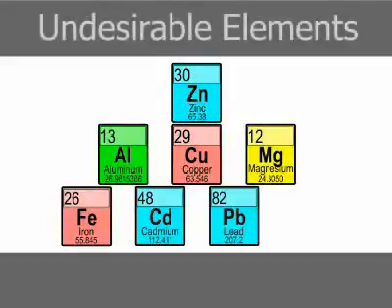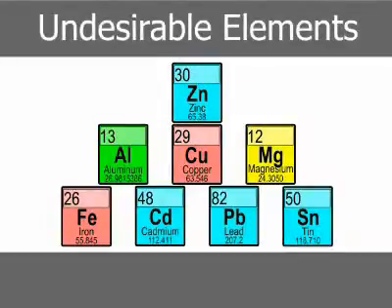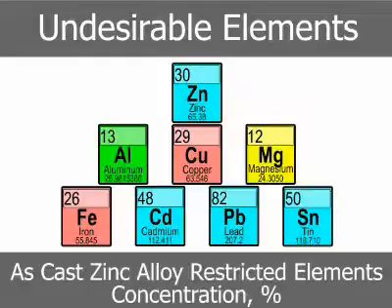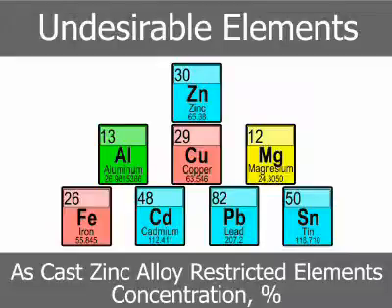Iron, cadmium, lead, and tin have been identified as undesirable elements and are restricted to low or extremely low levels. Higher iron contents form undesirable intermetallic particles. Lead, cadmium, and tin, even in very low concentrations, can cause intergranular corrosion in the crystal structure of the zinc-aluminum alloy system when magnesium is absent. The as-cast allowable levels of these elements are shown here.